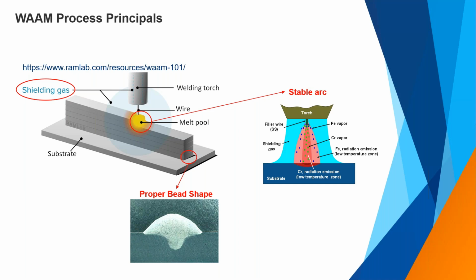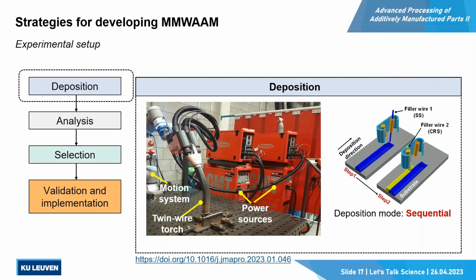each other. In the next slide, this is the deposition setup at KU. You can see the two power sources, Fronius CMT power sources, which are both connected to a twin torch. This torch can handle two wires, as you can see on the right figure. And now we are using two different materials. And the deposition mode is sequential. For example, first material A is deposited, and material B is deactivated, and then the torch moves the same path with deposition of material B.